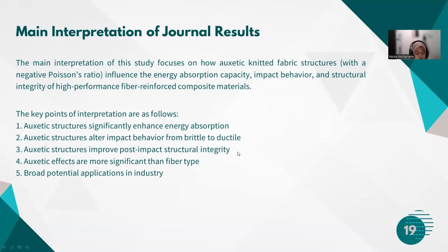Observations show that jersey composites experience matrix cracking and fiber breakage, whereas auxetic composites display a more intact surface without significant delamination. This means the 3D auxetic structure helps dampen and distribute impact stresses, reducing micro-damage around the impact zone. As a result, auxetic composites are more resistant to repeated failure and structurally more stable after impact.